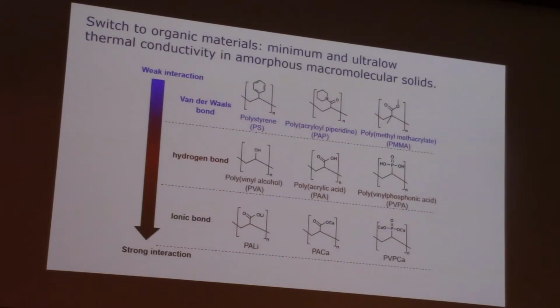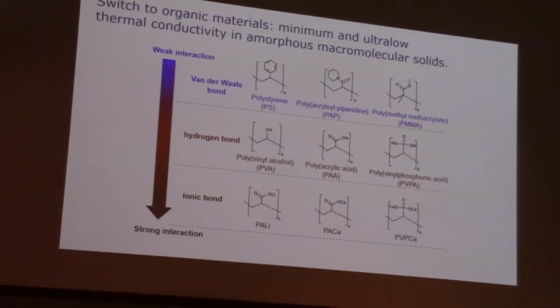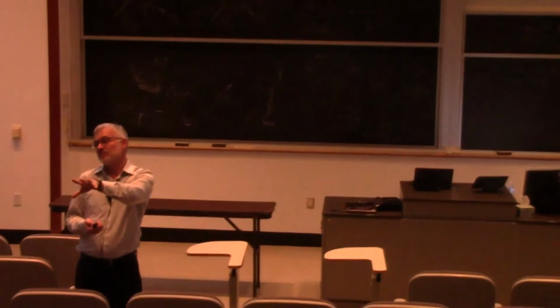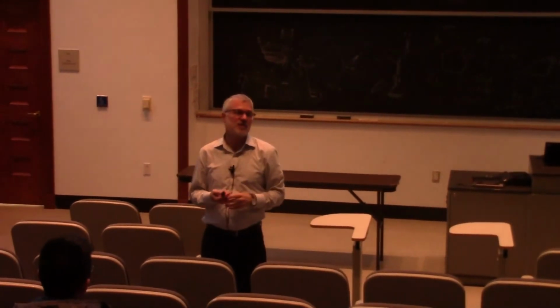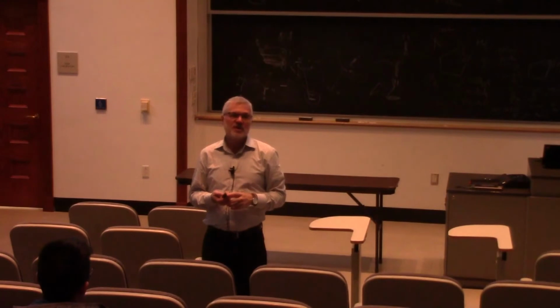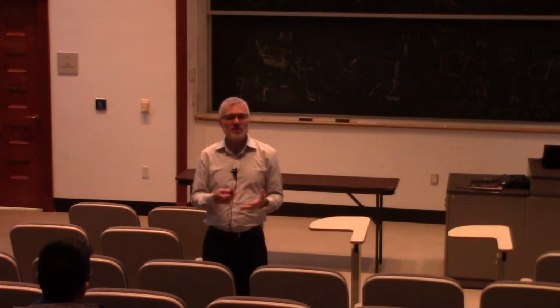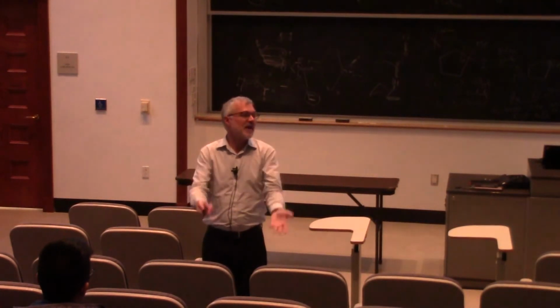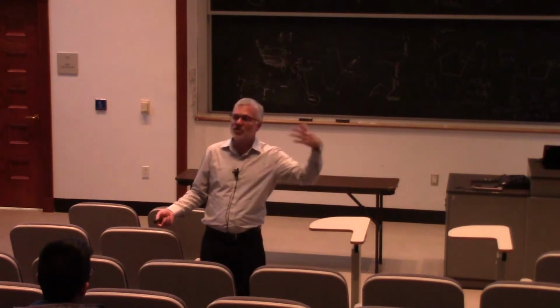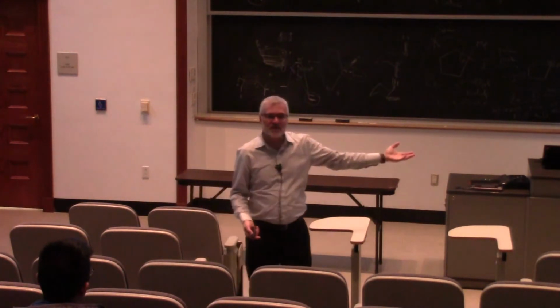Okay, and the reason we needed that is we want to be able to relate some of the elastic properties of the materials to their thermal transport properties. So again, this is maybe a way of looking at how well we can use this Einstein-like picture for thermal conductivity, which was predicated on speeds of sound, one of the inputs to that kind of model, to understand the thermal conductivity of soft materials. And can we find materials that have thermal conductivity much lower than what might be predicted by that kind of model?